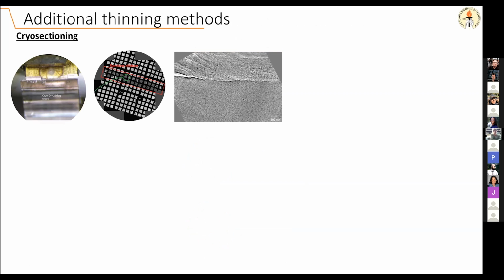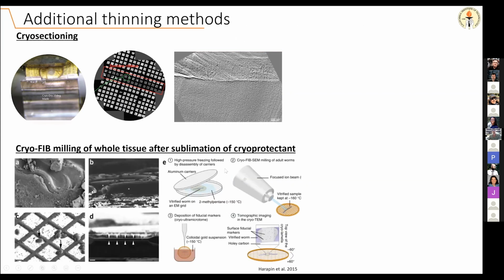Just to finish, additional thinning techniques. So one that's quite old now, but it's getting replaced by FIB milling, but it can still be very efficient if sufficient expertise is available in your institute. It's called cryosectioning. So here we high pressure freeze the sample and we cut frozen hydrated sections that we lay on grids. And then we perform the tomography on these frozen hydrated sections.